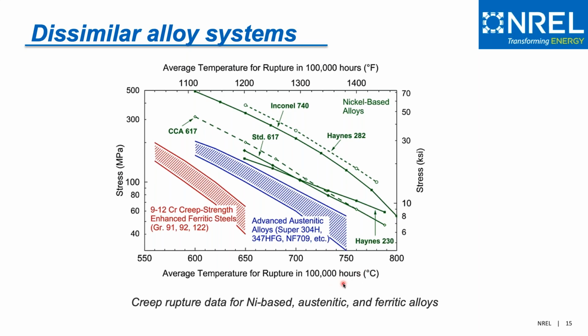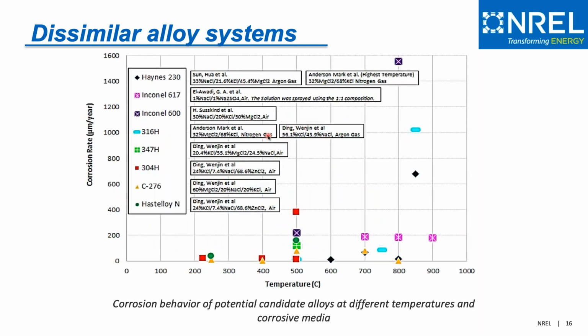100,000 hours. And this one is the creep rupture for, in particular, our nickel-based alloys and the austenitic and ferritic alloys. So in here, I see that, yes, Inconel 740H and the Haynes 282 are the top alloys for the high temperature. And here are also some of the properties that we consider when we are evaluating or doing the